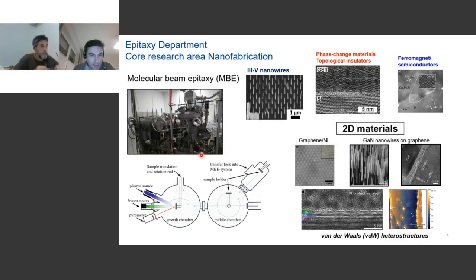I don't know if you can see that here, but you have some ports, in this case. This is a system where the effusion cells, where you load the elemental material that you want to evaporate, are loaded here. Usually in this case, the sample will be around here. This is an illustration of a typical system, for instance, used for growth of boron nitride, where we have the growth chamber where we put our sample inside. We are able to rotate the sample during growth, and also do some spectroscopy.